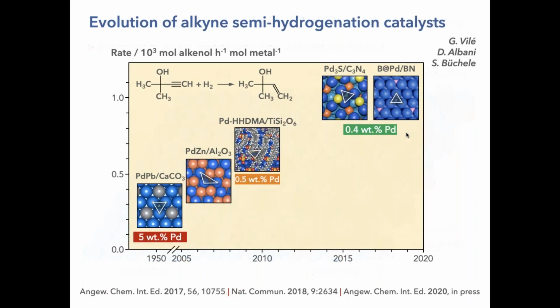And with that, we were able to go from the Lindlar catalyst with a certainly reduced activity containing a lot of palladium to systems that contain 1 order of magnitude less palladium and that are environmentally friendly. And these systems are characterized by the fact that they contain the same type of ensembles, trimeric ensembles of palladium, as you had in the Lindlar catalyst facilitated by lead.